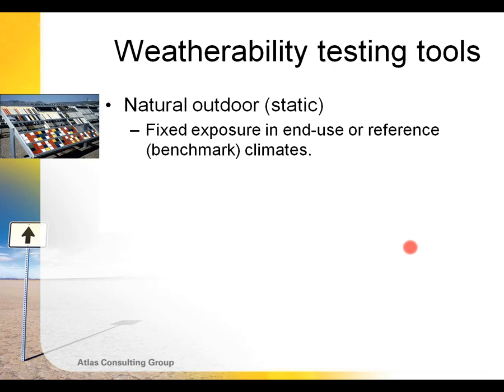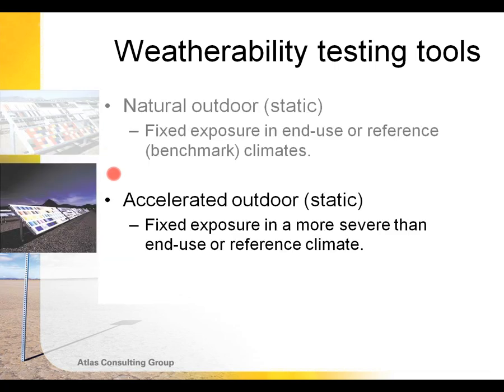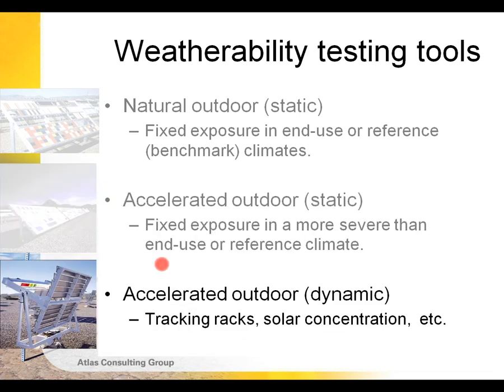Specifically for weatherability testing tools, we have our outdoor tests, which can be fixed position tests in various different climates. We can have accelerated outdoor tests where, if a product is primarily to be used in North Central Europe, for example, say a coating, and we test that coating on painted metal test panels in Florida or Arizona, they typically provide about four times the rate of weathering that we see in Northern Europe. So in 1 year of outdoor exposure in Miami, Florida, we can oftentimes get the equivalent of approximately 4 years of field experience of what a product would see in, say, Germany. There are a lot of caveats to that, so don't take it too seriously.